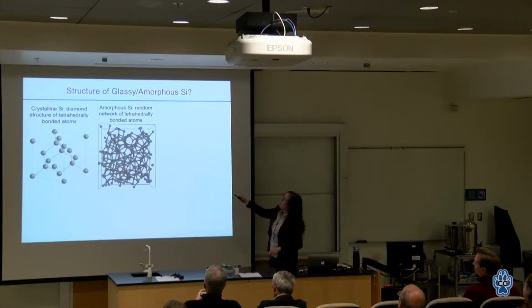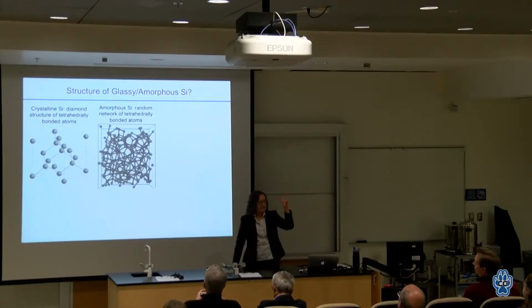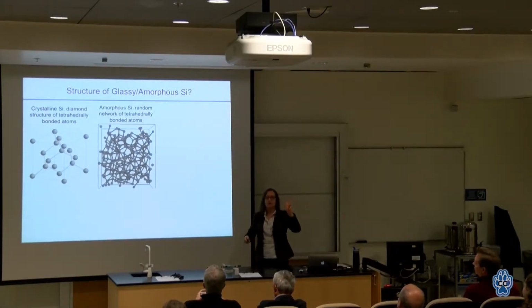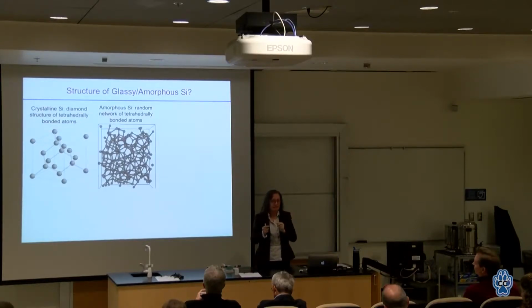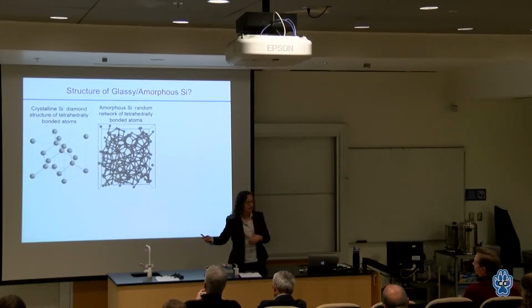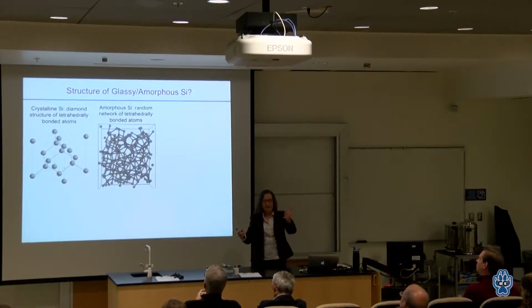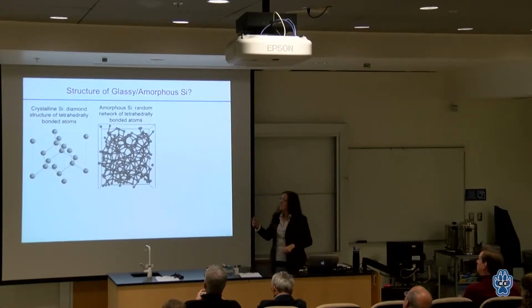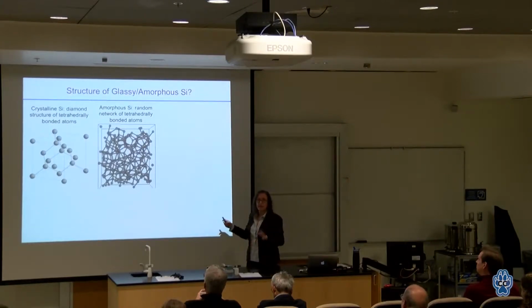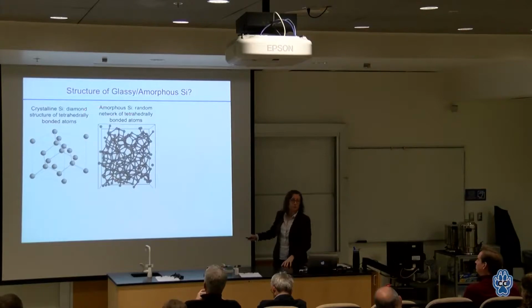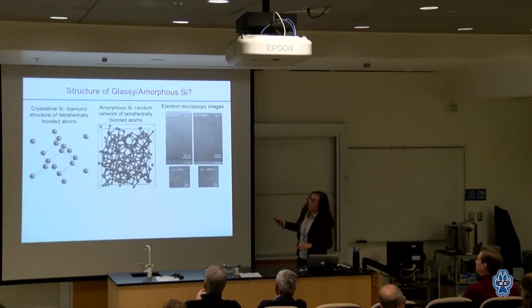And that's the crystal structure for crystalline silicon. Now, if I make it amorphous, you still have that same local order, that same tetrahedron, but it has to be not quite 109.5. In fact, it has been proven, I think mathematically, that you have to have a certain distribution. Instead of all the angles being exactly 109.5, there's a width to that, about plus or minus 8 to 10 degrees. That's quite a bit of broadening, but 109 plus or minus 8 degrees is still mostly tetrahedrally bonded. The angle is only a very small amount off of that perfect tetrahedron. The bond lengths are really preserved, so the silicon to silicon distances are almost exactly what they are in the crystalline state. The bond angle has just a little bit of variation, and that's enough to make this jumbled mess of a structure. So what does it look like if you see it?